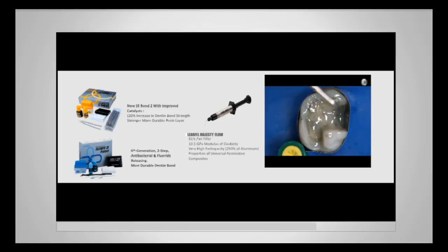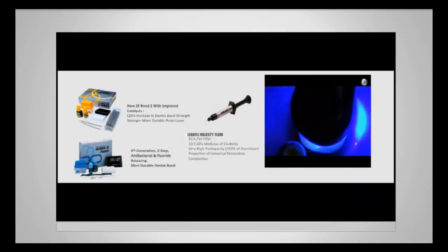Now you could add a little more to maybe block out a light undercut, or just give a nice flow to your preparation if you want to do so. You could add another millimeter layer or just a little bit, wherever you might feel is necessary. But initially, this first 1 millimeter layer is our immediate dentin sealing layer on top of our bond, and now we light cure that. And now I have immediately dentin sealed, or done IDS, on this restoration. It's that simple. And if you keep that in mind, what we just did, you really learned immediate dentin sealing.